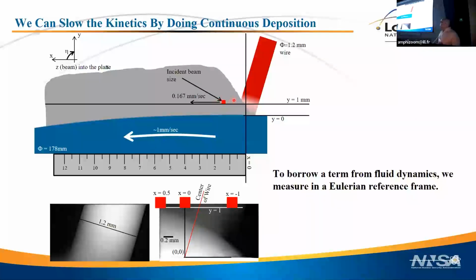And as you move from x equals 0 here, this is essentially moving back in time, right? As I move my X-ray beam, well, in reality, I'm moving the entire welder. It's easier to talk like you're moving the X-ray beam. As I move the X-ray beam away from the weld pool, I'm essentially going back in time or to cooler material. Okay, so I can do a transformation from where I measure to what time I measured at relative to solidification.